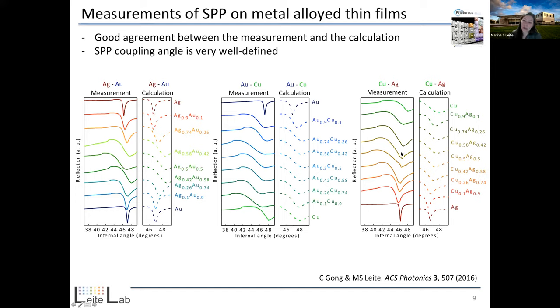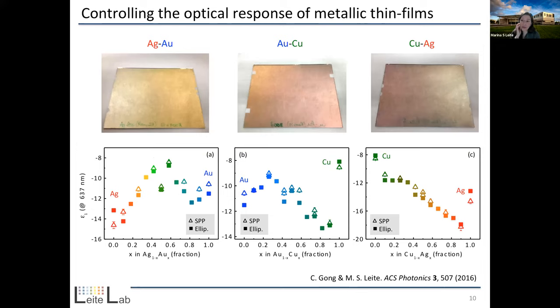You know, there's a bit of noise because there is actually more loss probably, right, since this data has been shown here normalized. But again, the position, meaning the internal angle at which the minimum reflection occurs, agrees very well with our calculations. So if we now put these two measurements together, the ellipsometry measurements and the SPP measurements that I've just shown to you, the surface plasmon polariton, and I'm representing the second one by the triangles here, since we use a prism for that, and the ellipsometry by a little solid square. If we do that for at least one wavelength, meaning 637 nanometers here, we see a very good agreement between the two.